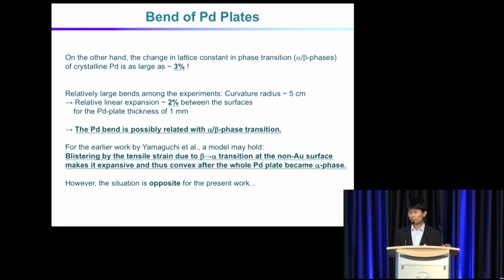And then Yamaguchi mentioned that in his case of the bending direction, probably blistering by the tensile strain due to the beta to alpha transition at the surface of the palladium plate, which was not deposited with gold, made it expansive, and then this became convex after the whole palladium plate became alpha phase. So such a blister made the bend. That was one possibility, but our bending direction was opposite. So we cannot fully explain the result.